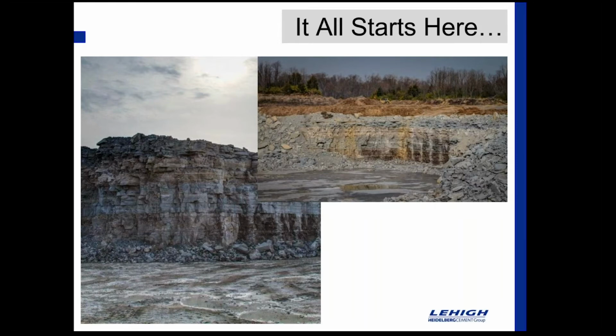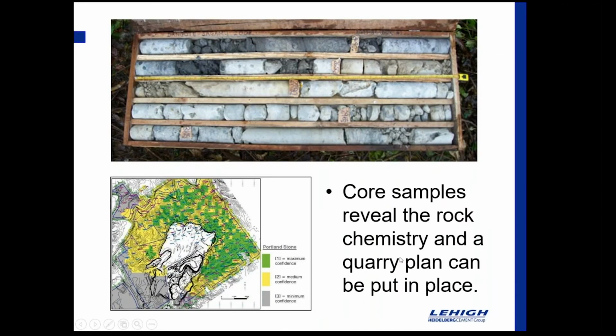Almost every place you see a cement plant, there's a hefty limestone source either on that grounds or very, very nearby. And so because of the abundance of limestone, we've got to have an idea of how we're going to remove that overburden, how we're going to expand that quarry, what's that going to look like when we start to plan how to mine this material. And so one way that we do that is to take core samples where they'll drill down through the rock and they pull out these core samples, and that can reveal the chemistry as they go down through different layers of the sediment. And then a quarry plan could be put into place. And so you see the bottom left here, there's a map of a two-dimensional quarry plan, and that would be how the cement plant would choose to expand and bring material up for use in the cement manufacturing process.